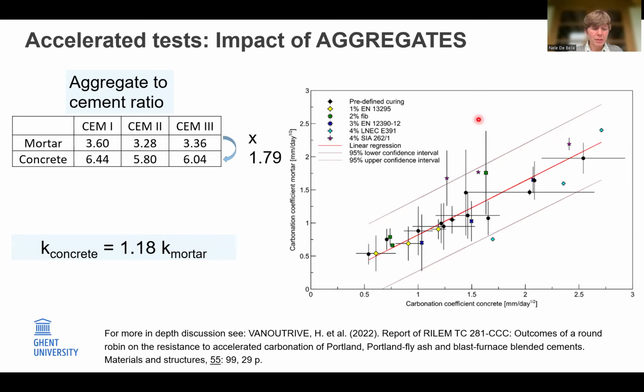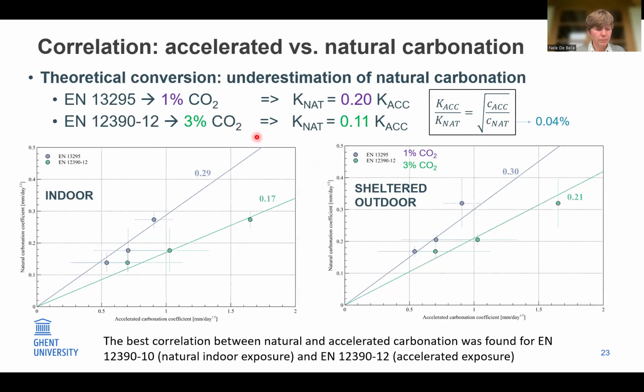We have also compared the carbonation rate of mortar and concrete. And actually, the carbonation coefficient of concrete was 1.18 times the one of mortar, with the aggregate to cement factor being about 1.8 times higher for concrete than for mortar. And actually, in a natural carbonation test, the same factor was obtained.